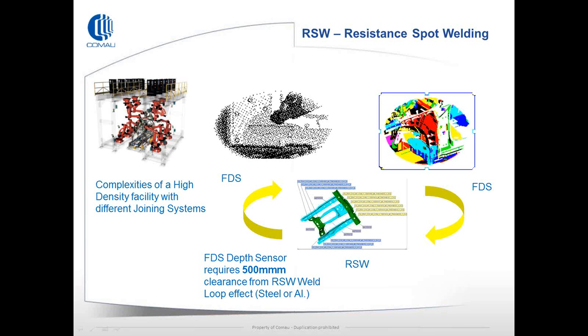For example, here we've got FDS, resistance spot welding and FDS. A consideration needed for the FDS process is that the depth sensor, which is a key component in the FDS application, requires approximately a 500mm clearance loop to the nearest resistance spot weld if you're doing it simultaneously. Just a key point to be aware of.